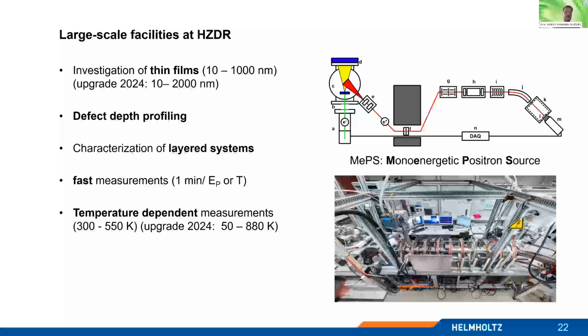And here is some information about this mono-energetic positron source, which is also used for defect depth profiling, which means we can vary the implantation energy of the positron, and therefore you can see stepwise, energy-wise, what happens from the top to the substrate of your material. And here we have a measurement time which is quite fast, which is 1 minute. I skipped this part for the source-based positron setups; there it's approximately 15 minutes to 12 hours, depending on the resolution or on the details you would look at.